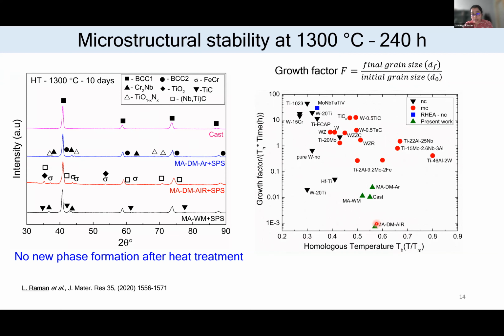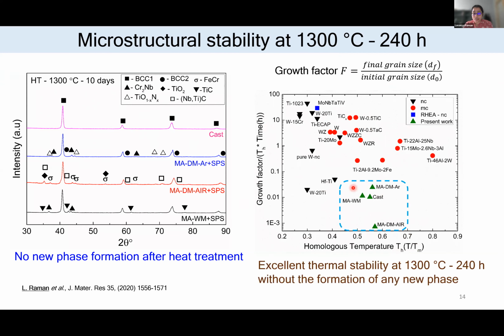So we have compared the alloys that we made with the alloys in the literature. We can see that they have the least growth factor, which means they are really stable at 1300 for a sufficiently long duration. So this helps us in establishing the structural stability. So now we know that this alloy has different kinds of phases and is really stable. Now we have to understand the deformation mechanism of this alloy.